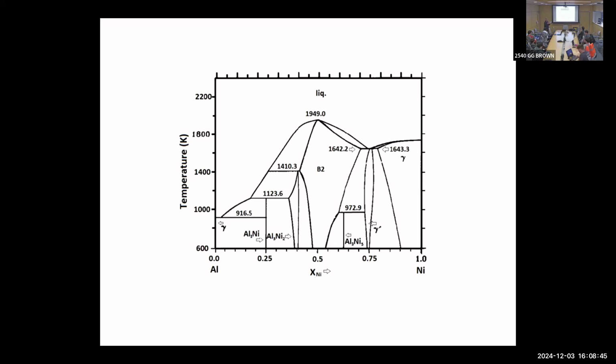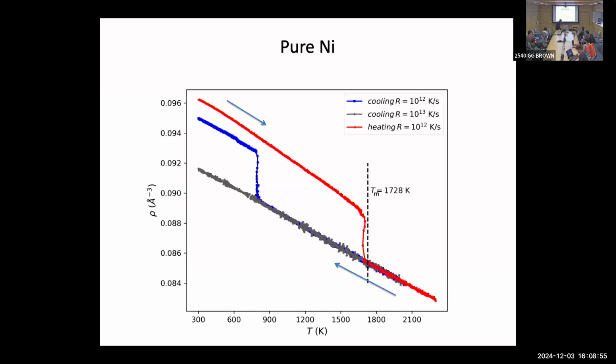Similar questions happen with glass formability. What is the glass formability in the middle regions of these phase diagrams? In general, what we're going to do in the computational studies is cooling. You could do heating, but we're going to do cooling. So we're going to take a melt, a disordered liquid, and cool it at a certain rate. That is, we're going to suck temperature out of the system, and we're going to see whether it crystallizes during that process. And that question depends on rate.